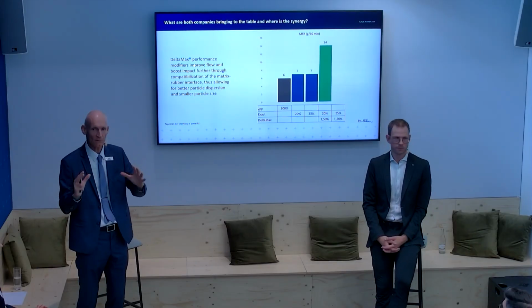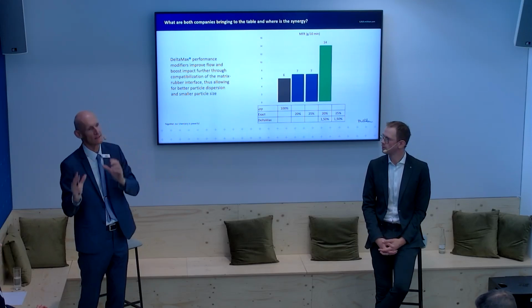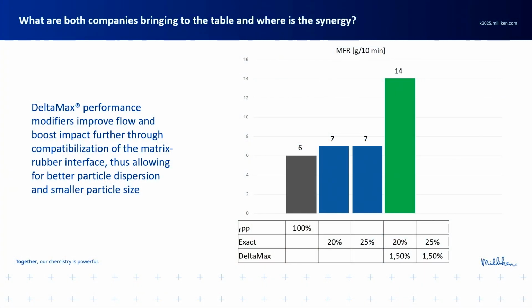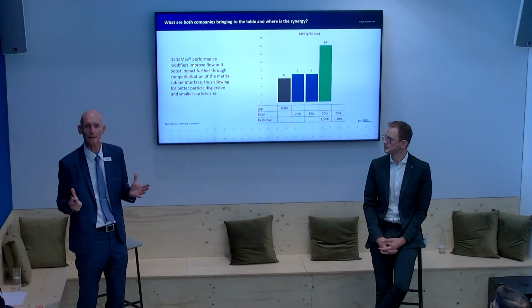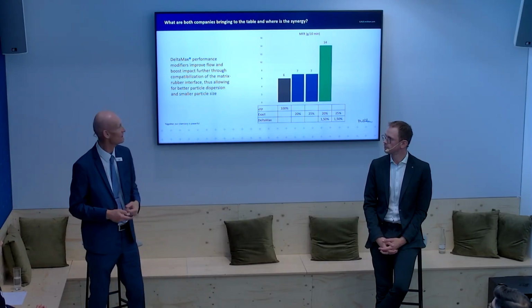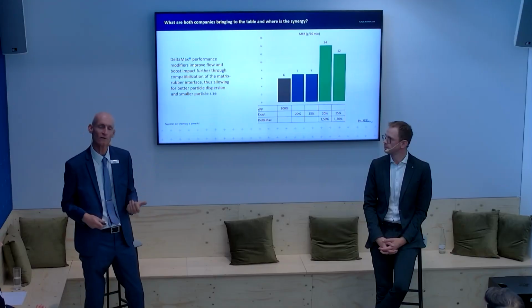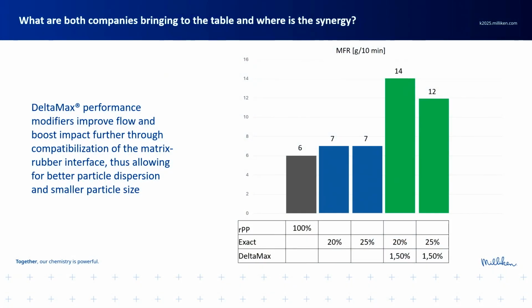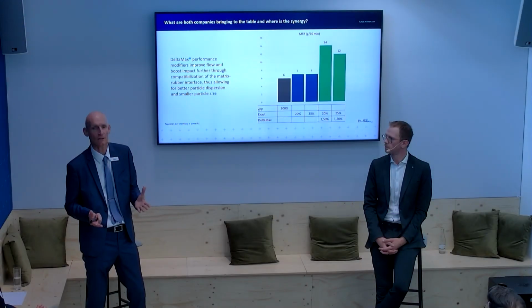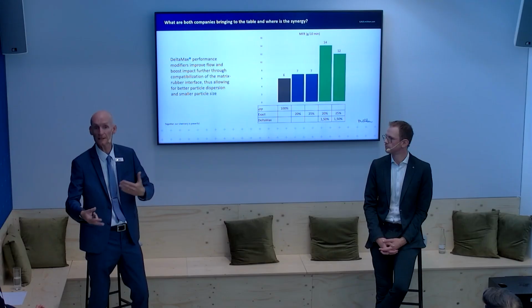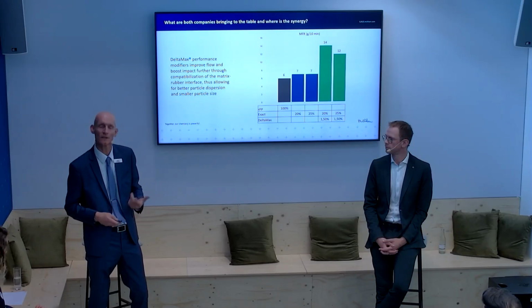Delta Max modifies the flow and, at the same time, the compatibilization of the rubber phase, Exact, good low temperature impact, with the recycled polypropylene. That's what it's going to do. And we can do that with both the blends of 20 and 25%. And you see that we kind of double the MFR. And that is going to give you the cost reduction that you look for. Because you have to increase the recycled content, so you're stuck with that. You have to then improve the properties. And then you have to bring the productivity where it needs to be to compete with virgin material as much as possible for the economics.